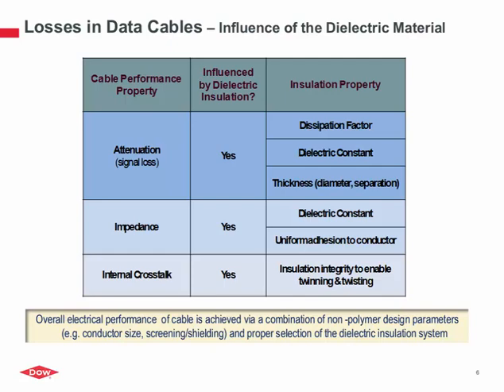Internal crosstalk also is affected by the insulation, and it comes through more on the mechanical integrity, because to reduce that, there needs to be twinning, twisting, and these induce radial forces on the insulation, so compressive forces. And if the insulation is not of robust mechanical properties, the foam insulation itself can collapse. So as I mentioned, this is not all. The overall performance of the cable is achieved by a combination of both, right? The non-polymer design parameters, but also the proper selection of the insulation material itself.